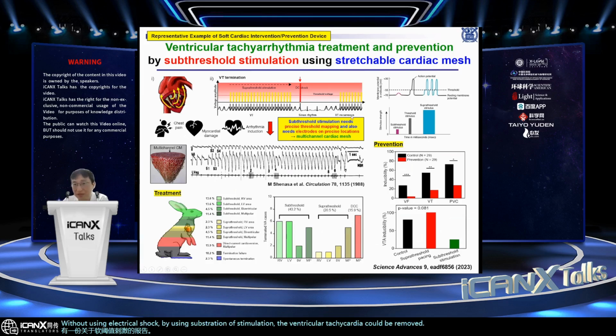Let me explain the concept of subthreshold stimulation first. There is a threshold voltage to modulate the beating of the heart. If the voltage of the electrical stimulation is higher than this threshold voltage, then we can modulate the heart motion. Of course, capture pacing should use higher voltage, and electrical shock should use much higher voltage than the threshold voltage. But subthreshold voltage stimulation means the voltage is lower than the threshold voltage. That means although we apply stimulation, and a very small current flows, the natural motion will be maintained rather than modulated. And that small current can remove VT. And since the current is very, very small, chest pain and myocardial damage can be prevented.